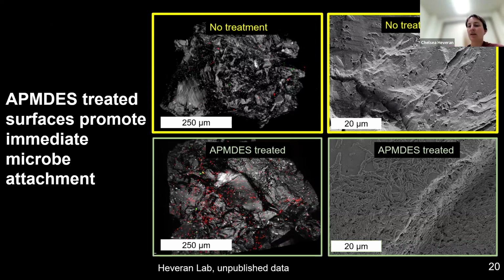And on the right-hand side, we have scanning electron microscope images. So with no treatment, that means we're biocementing the sand, but it didn't have the surface treatment first. We don't see very many microbes at 15 minutes after we put the sand in a biomineralizing solution. And that makes sense. That's really fast for this. When we treat the surfaces, we have this immediate attraction and almost a monolayer of cells over the surface.